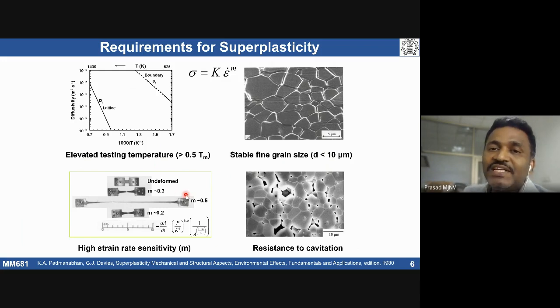m has a physical significance: resistance to flow localization increases if you have a material with high strain rate sensitivity. These are interrelated. The finer the grain size, the higher the strain rate sensitivity. The strain rate sensitivity is going to be higher at elevated temperature in fine grain materials.